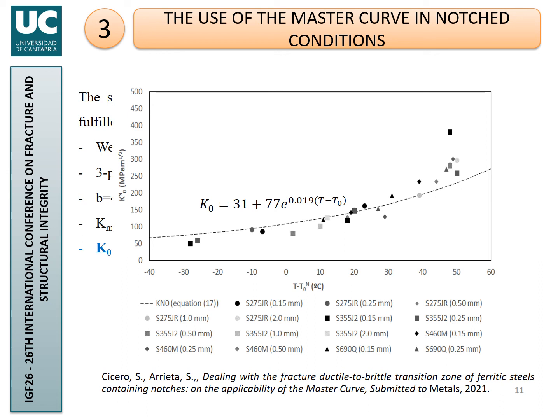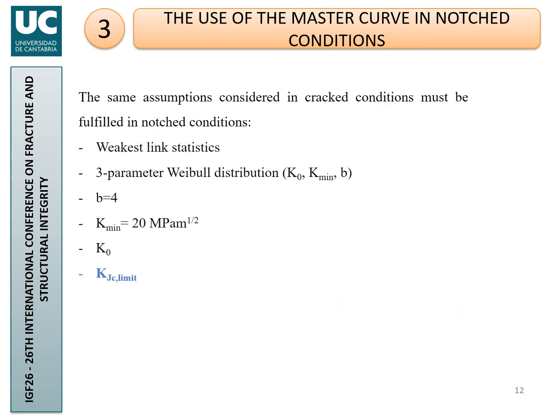Of course, we will need more experimental sets, and probably the curve will change a little bit for notches, but it looks reasonable to use this same expression for notches as well. And finally, concerning the censoring criterion, it is something similar to K-min; considering the same expression for notched specimens will in any case be a conservative assumption. So we may use the same expressions for notches.